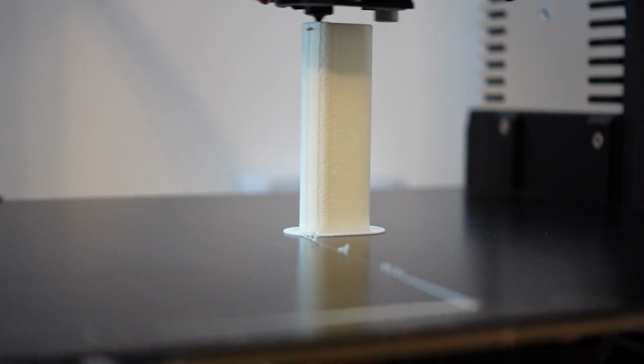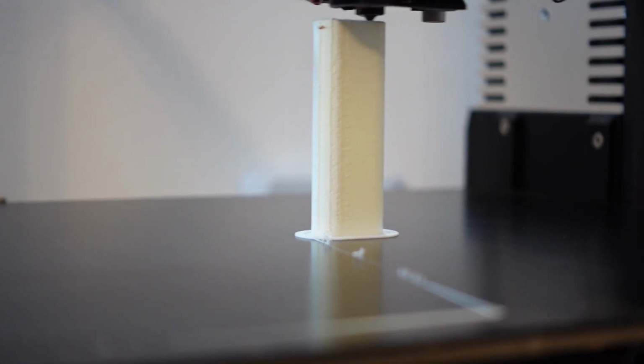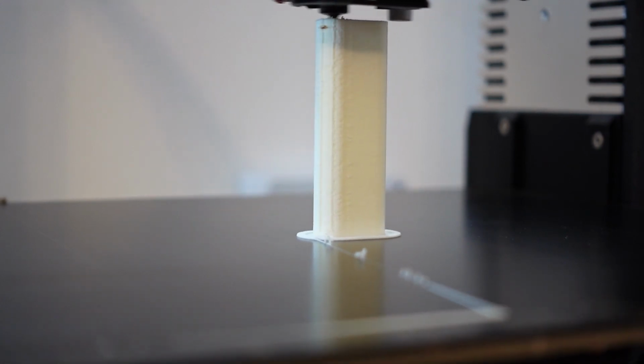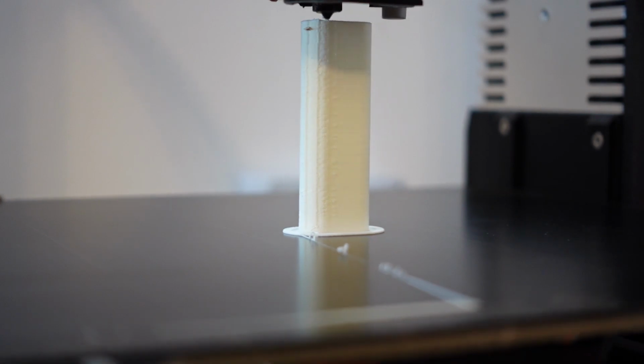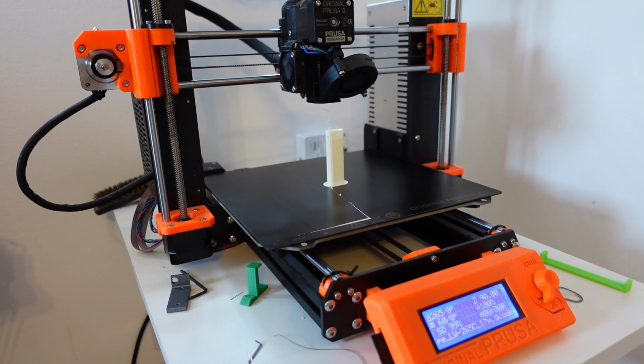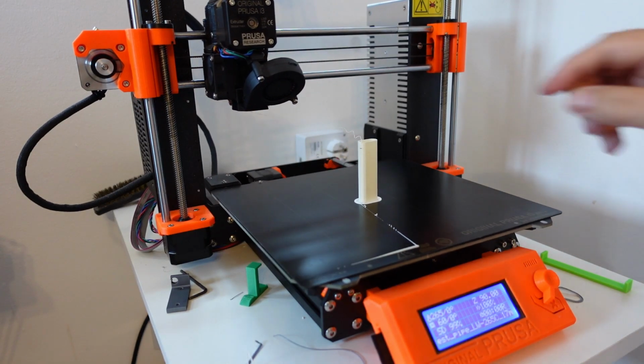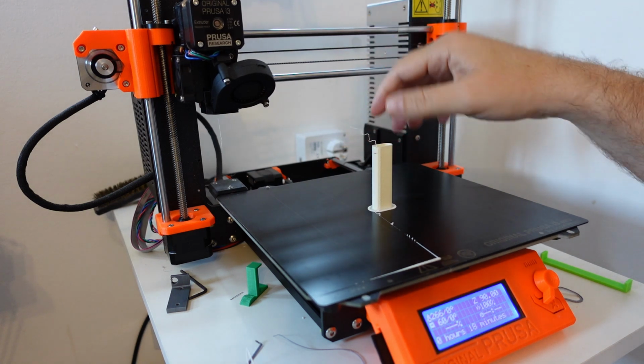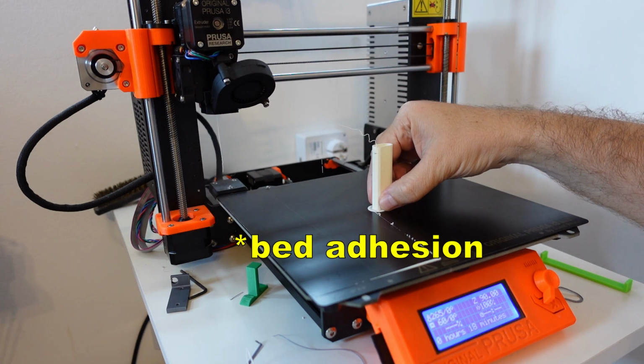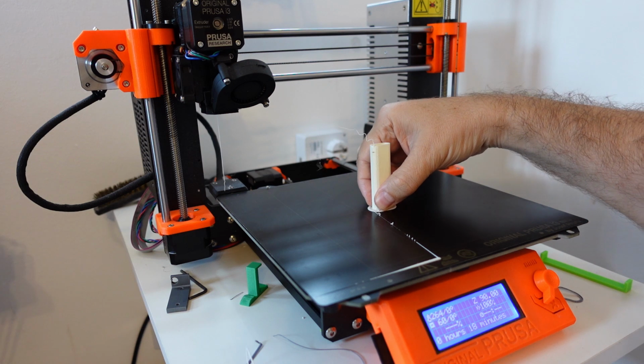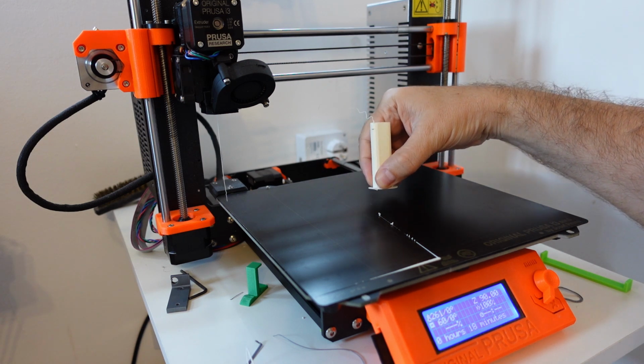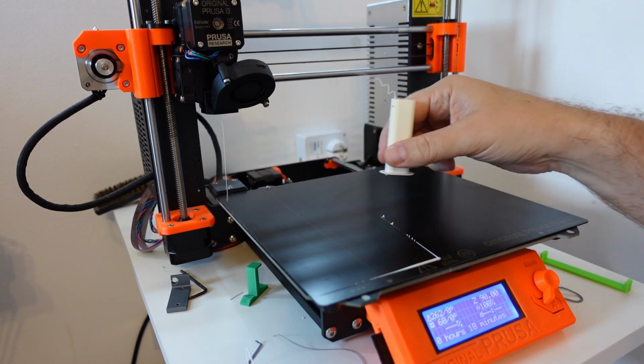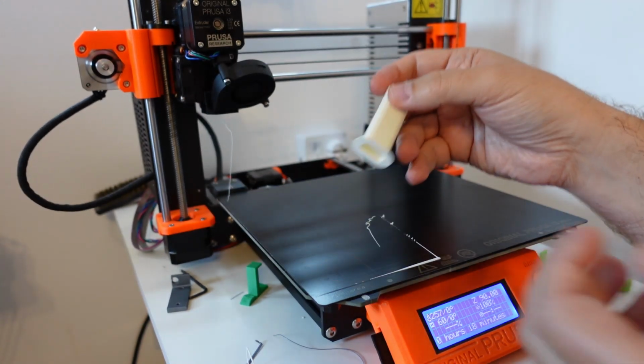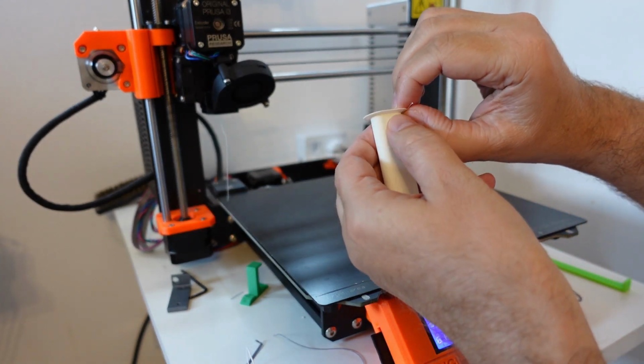And it's almost finished. It has constant quality from the beginning until the top, even if the layer printing time is quite short and the cooling fan is set only to 20%. The string. Let's check the bed adhesion. Okay, that's fine. Wow, it's really light. I will remove the brim and I will measure the weight.